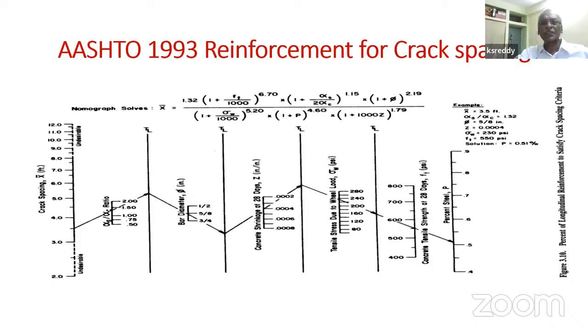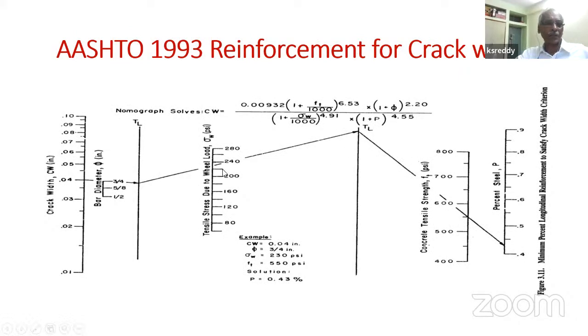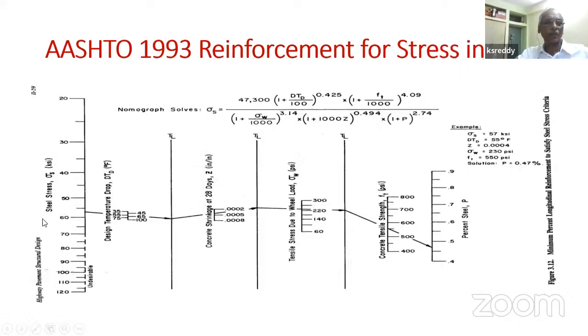The AASHTO 1993 has nice nomographs available, which is nothing but solving this equation. This is for crack spacing. I will not go into the details of what those variables are. Obvious variables are thickness, coefficient of thermal expansion, the reinforcement details, and the concrete strength details. Similarly, you can estimate crack width. You can estimate the steel stress so that the steel doesn't get ruptured.